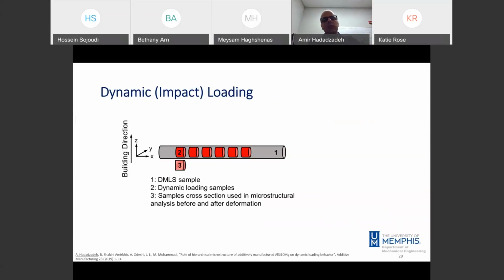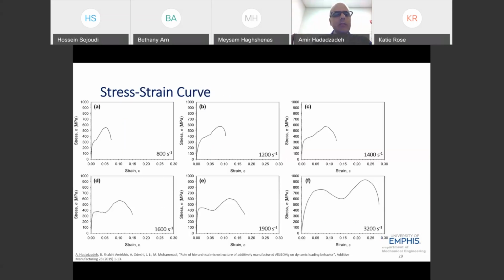So after doing quasi-static tests on the material, I also did some dynamic or impact loading, high strain rate deformation on the sample. And I chose the horizontal rod, as you see here. Some cylindrical samples were machined out from that rod, and by using the split Hopkinson pressure bar, we conducted high strain rate deformation on the material at different strain rates. So here, stress versus strain at different strain rates from 800 per second up to 3200 per second. So there are two deformation regimes.